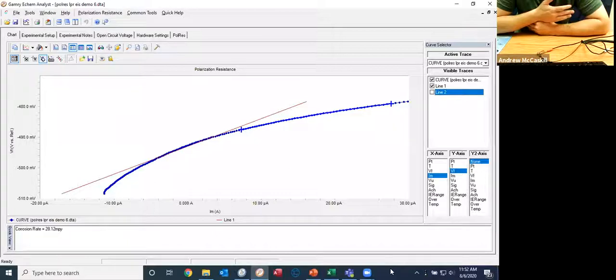So is LPR destructive? It's certainly active. There's no doubt about that, but I can't say for sure I would call it a truly destructive technique. But you certainly can see corrosion from the system. There's no doubt about that. So the system is changing. But depending on your specific system, you could see things quite differently. It depends on your substrate and your solution as to how your system is reacting to such an experiment. Okay, that's fine. Good. Thank you. You're welcome.